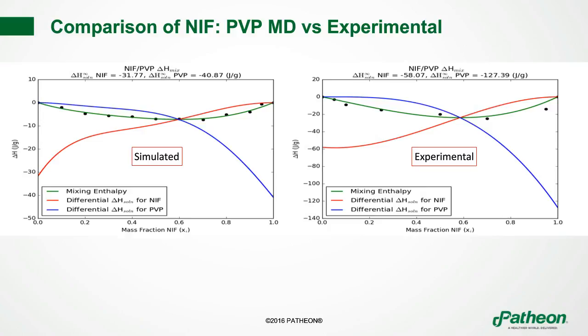And the blue line and the red line are just the differential heats of solution for nifedipine in red and PVP in blue. What we care about mostly is the infinite heat of solution at infinite dilution. So for nifedipine, it's around -31, and for PVP, it's around -40. You compare that to what we calculated experimentally, we've got -58 for nifedipine and -127 for PVP. So the energy values are not quite the same, but they're trending in the right direction, and we think we have information and understanding as to why we don't actually generate the same energies from the simulation as the experimental. But what's important is that we get the exact same behavior, and we know that we can tweak these simulations to try to further validate with the experimental data that we have.